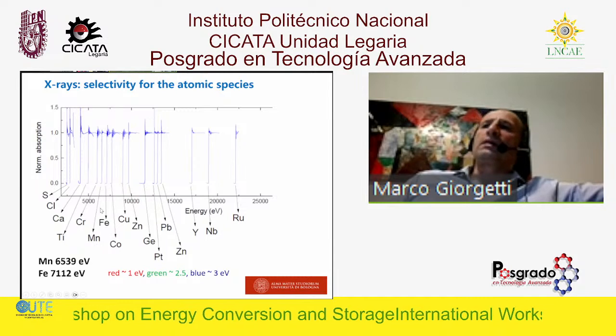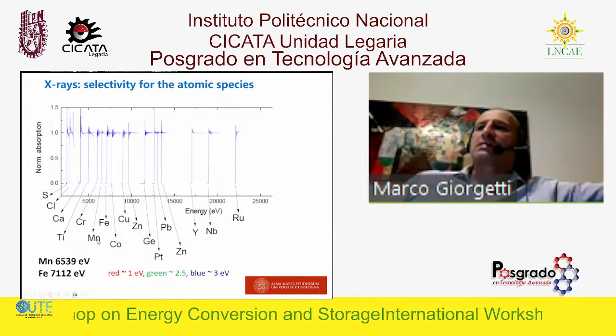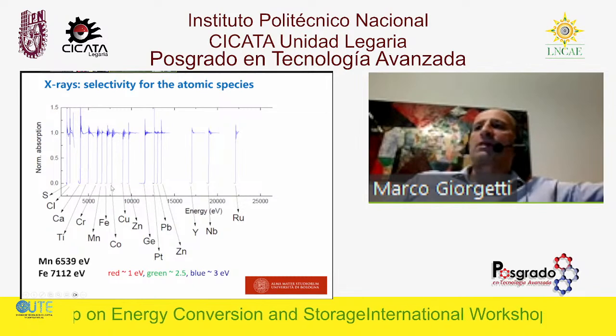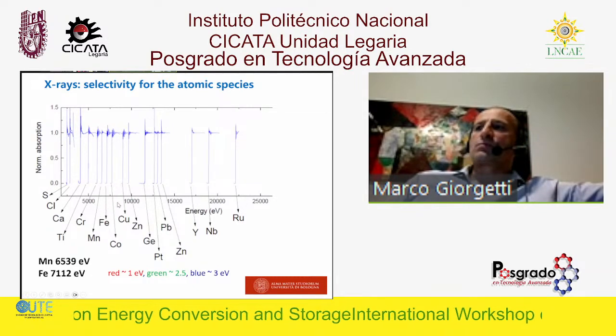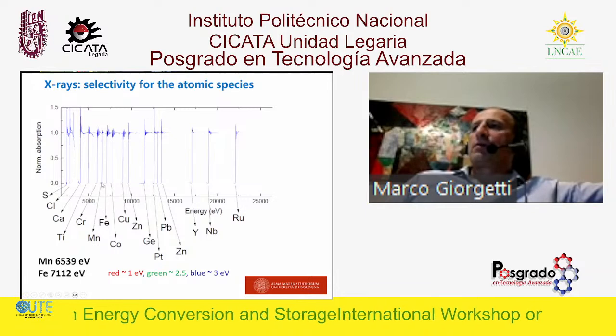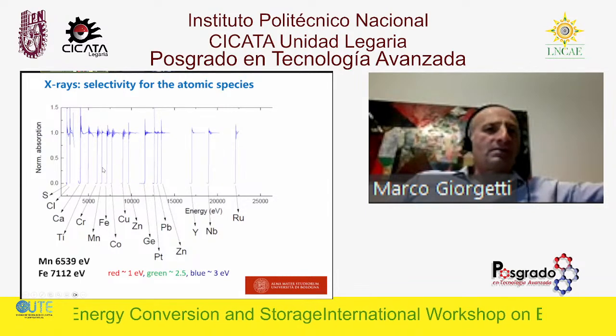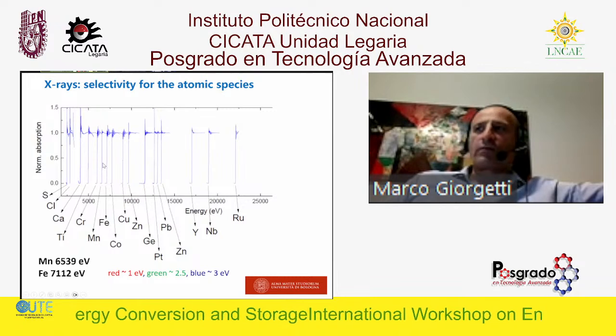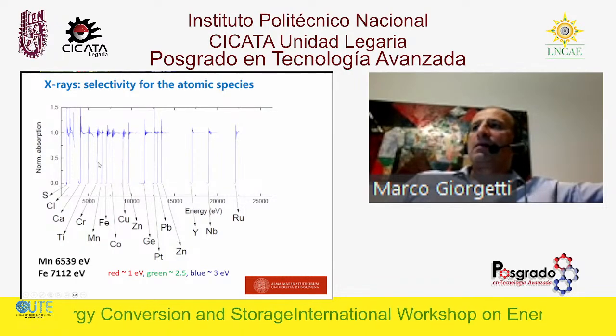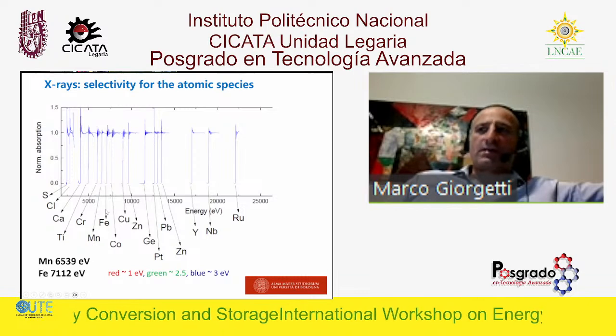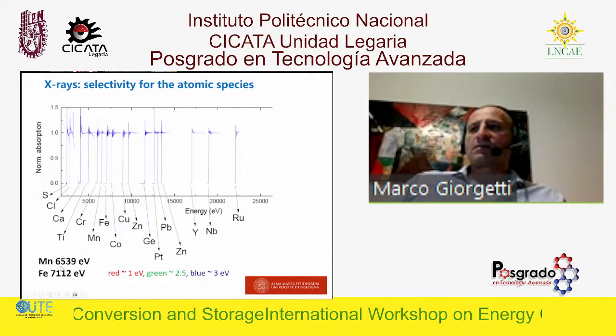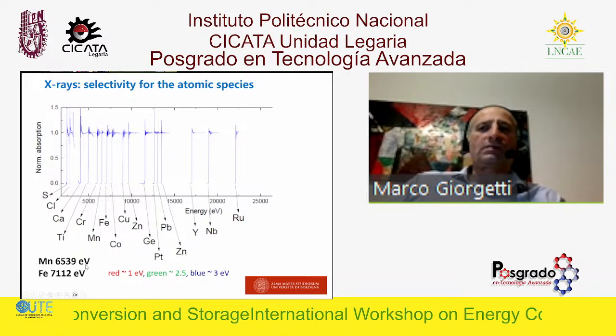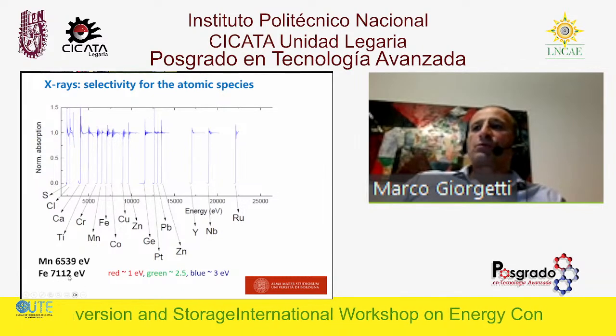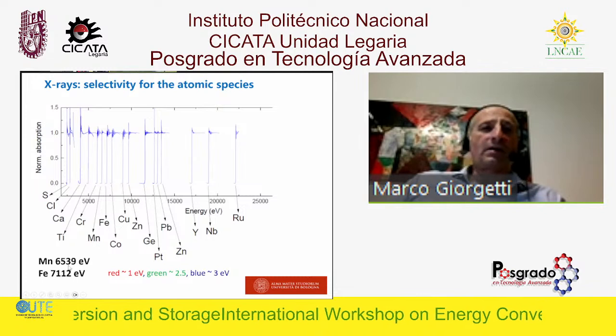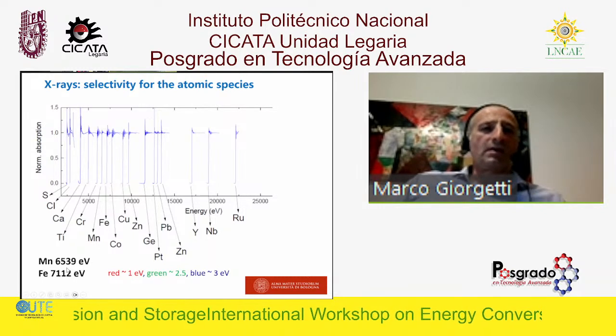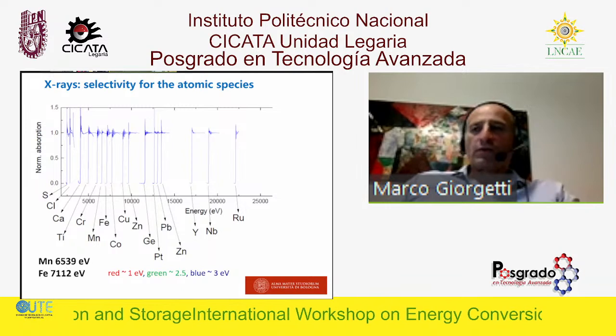Just to tell you the difference, pick, for instance, manganese, iron, or cobalt. They are at Z plus 1, Z plus 2. So the edge energy, I mean the energy that is necessary to eject one s core electron from manganese, iron, cobalt, they differ really a lot. For manganese, that energy is 6539 electron volts. For iron, 7112 electron volts. So they are apart by about 600 electron volts. 600 electron volts is an enormous quantity of energy.